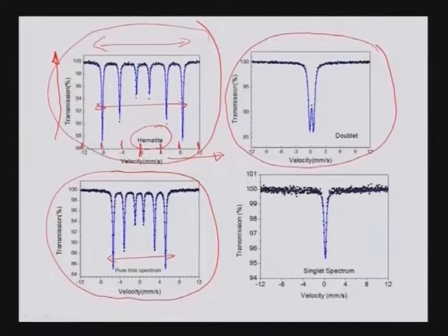This spectrum is a 2-line, a doublet spectrum, and this results when the solid has a non-cubic crystal structure and is non-magnetic as well. Magnetic will split in 6 parts. This is the kind of spectrum you get, for example, for iron in clay or iron in some compounds, iron carbonate and other things, or olivine or pyroxene. Yesterday I was talking of Fe2SiO4 olivine.